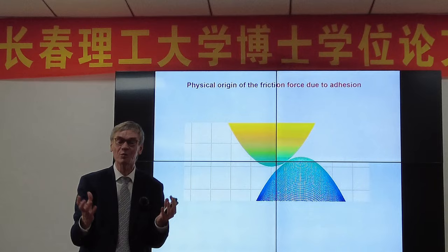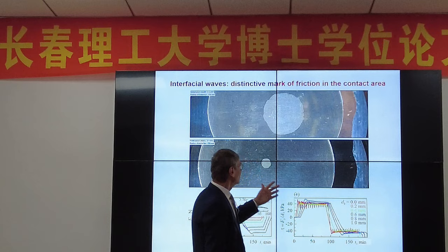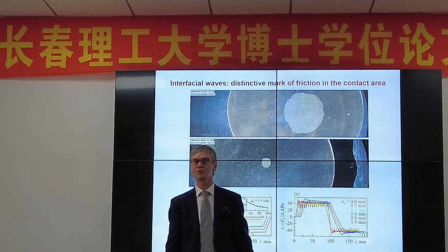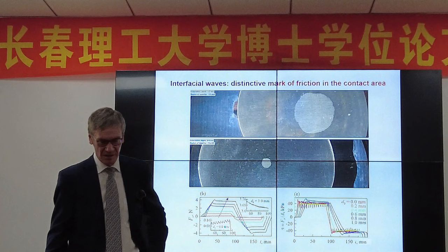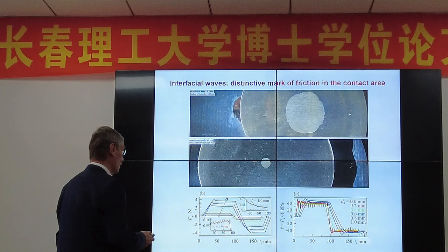And in experiments, we can really show that there exists, independently of how we do it, a tangential force contribution proportional to the area, characterized by some characteristic tangential stress. For the experiments which we did, it was approximately 40 kilopascal.